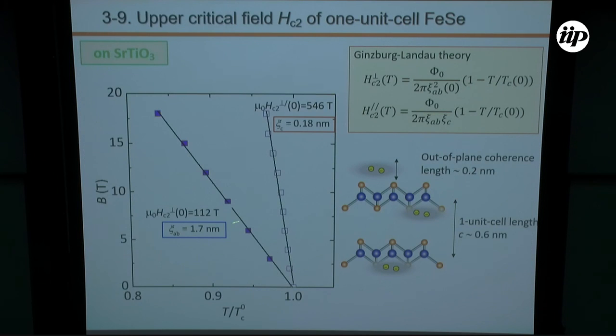Indeed, if we plot the upper critical field as a function of temperature, the data looks like that. And from this data, we obtain the in-plane coherence length of 1.7 nanometers. And using this length, we obtain the c-axis out-of-plane coherence length of almost 0.2 nanometers, which is much smaller than the c-axis length. This situation is very similar to the situation of the cuprates, where the Cooper pair is confined in the one layers. Maybe this situation can be related to high temperature superconductivity.